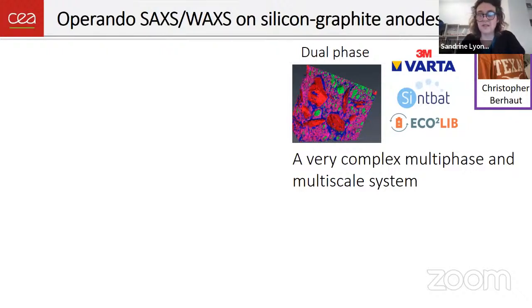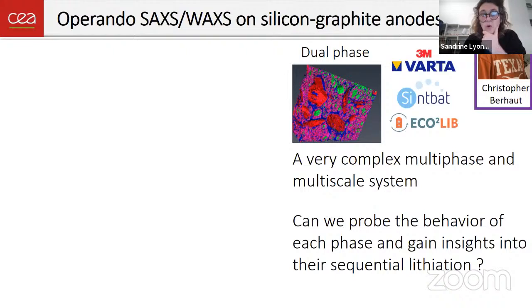is much more complex. This is now a composite material where we have graphite and silicon. You see maybe on this microscopic image some graphite chunks here, which are quite big, micron-sized, and you have a phase of silicon that is very complicated with nano-organized silicon channels. So it's a multi-phase and multi-scale system, and our question was, can we probe the behavior of each of these phases in this kind of complex material? And can we gain insights into the sequential lithiation of these materials?